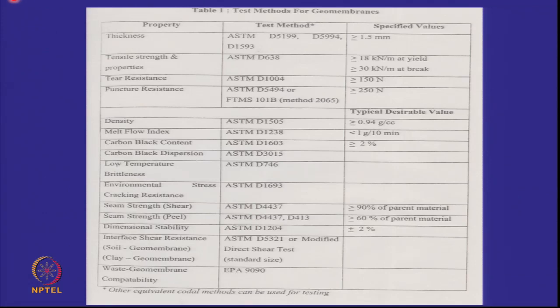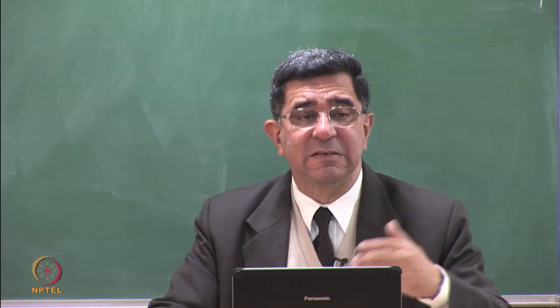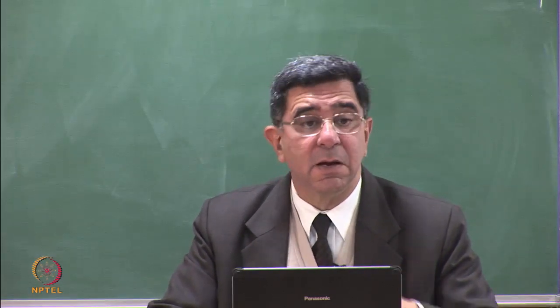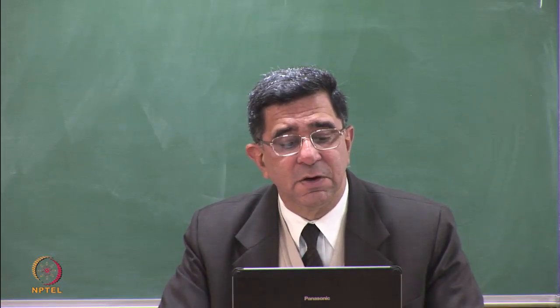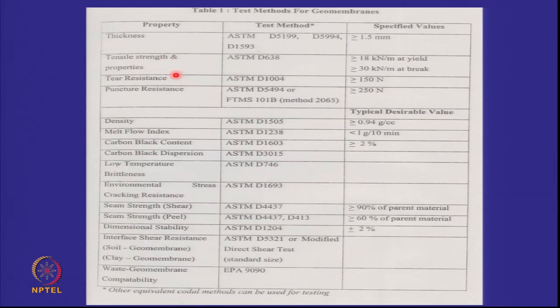And if I look at this table, I will not go into details, but just like we test soil, grain size distribution, density, specific gravity, plasticity, water content, strength, compressibility, permeability, there are a series of tests which have to be performed on geomembranes. Thickness, tensile strength, tear resistance, puncture resistance, density, melt flow index, carbon content, brittleness, environmental stress cracking, seam strength, dimensional stability, interface shear, waste to geomembrane compatibility. Some of these are routine, some of these are special tests. But just to get an idea, a 1.5 mm thick geomembrane will have 18 kilonewton per meter as its tensile strength.